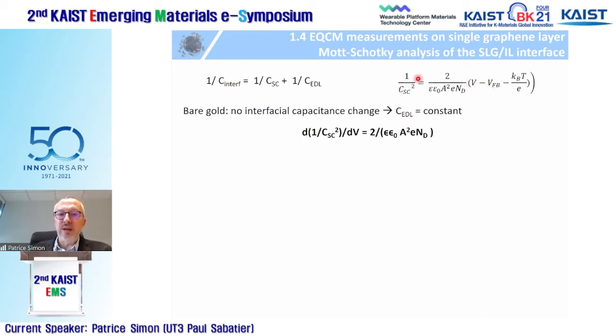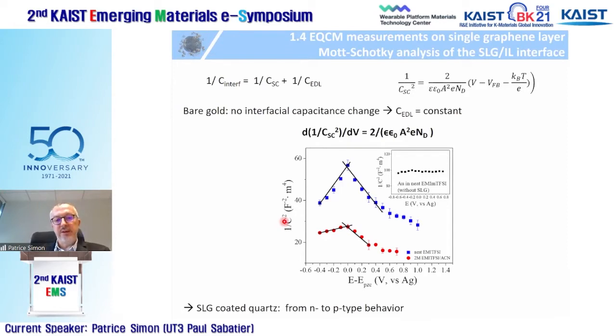And then, if you take the derivative of this expression, you can say that the derivative of 1 divided by C interface is in fact the derivative of 1 divided by CSC, the space charge capacitance, because the double layer capacitance is constant. And then you can plot the derivative of 1 divided by C squared versus V minus VFB, or E minus EPZC. And what you see here is the plot for neat EMI-TFSI, and this is the plot for EMI-TFSI in acetonitrile. When you have a single graphene in contact with this EMI-TFSI-based electrolyte, you move from N-type to P-type behavior when you cross the PZC. This is the first information.